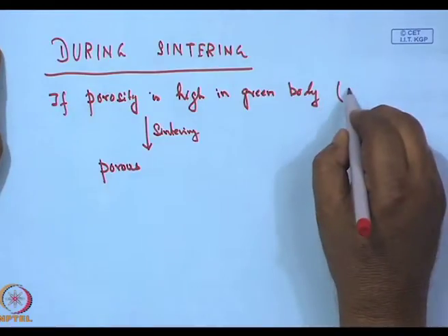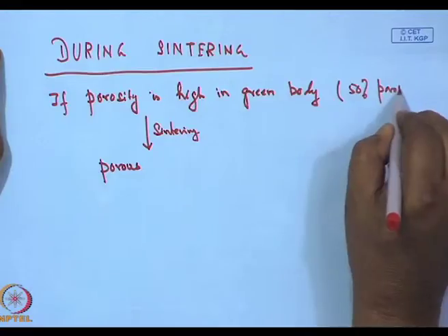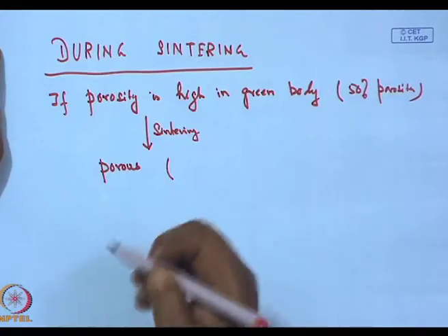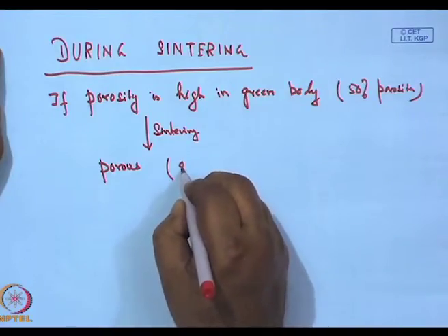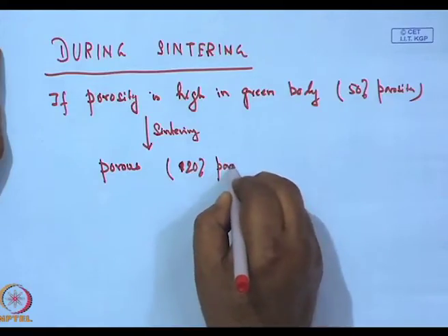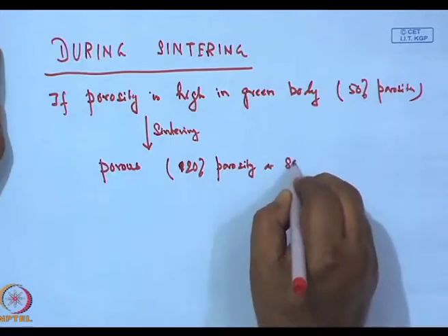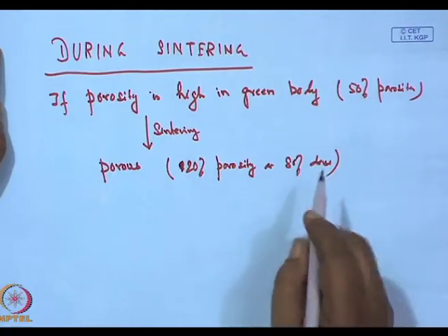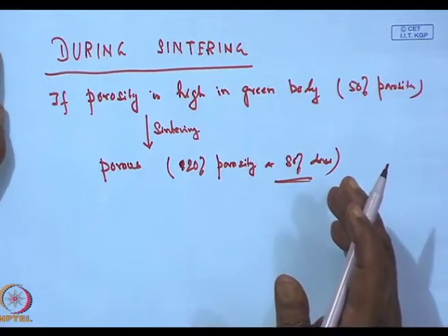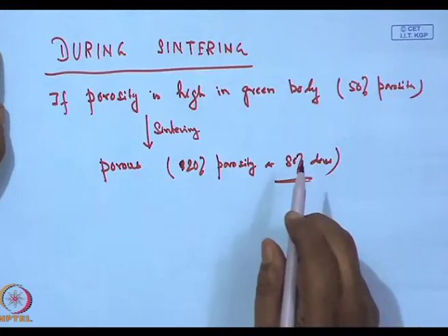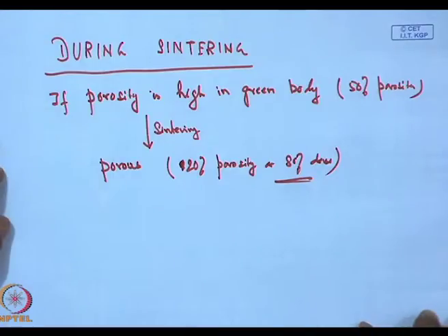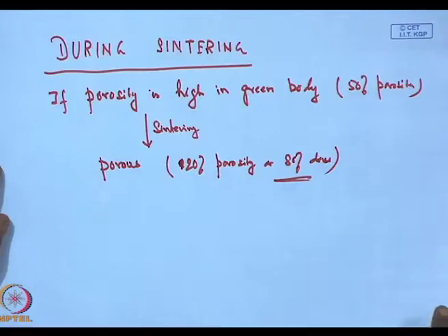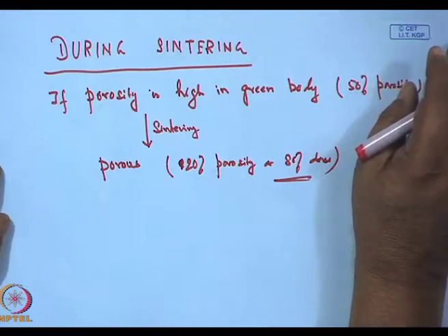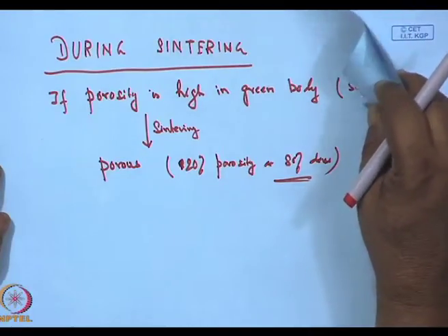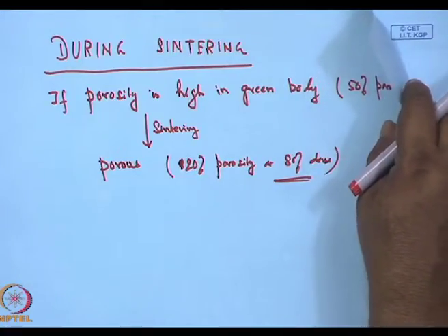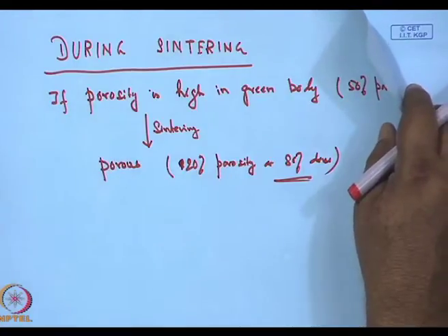If say 50% porosity is there, I may drive this 50% down to 20% porosity, or 80% dense. Yet we are very far away from the theoretical 100% density. This is simply, as I said, due to particle packing problems, the lack of uniform pressure during pressing, and as a result, differences in sintering rates at various places, and the porosity remains about 20% or so in spite of the best efforts.